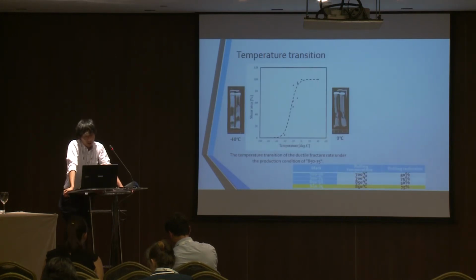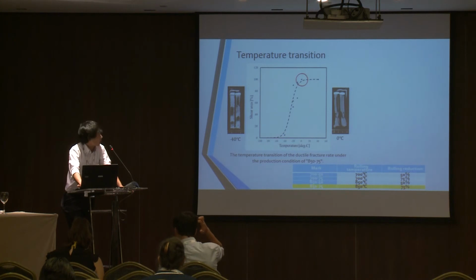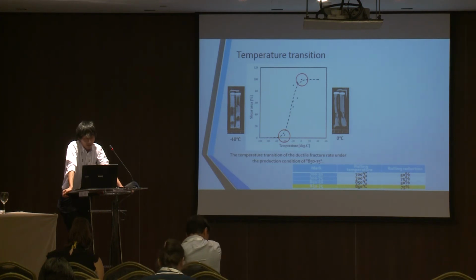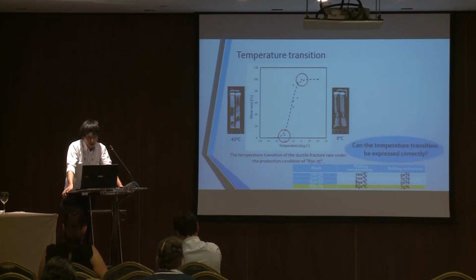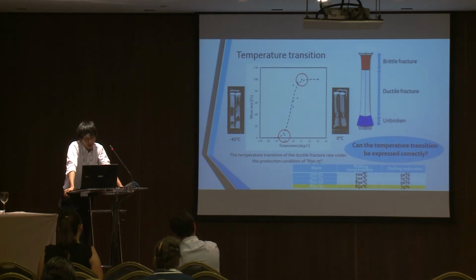This graph shows the temperature transition of ductile fracture rate under the production condition of 850-75. From this graph, it's understood that almost all fractures are ductile at 0 degrees Celsius. But almost the entire fracture surface is brittle fracture at minus 40 degrees Celsius. In this paper, we analyzed the conditions of these two temperatures and examined whether the temperature transition can be correctly expressed. In the analysis result, the brittle fracture surface is shown in red, the ductile fracture surface in gray, and the unbroken surface in blue.